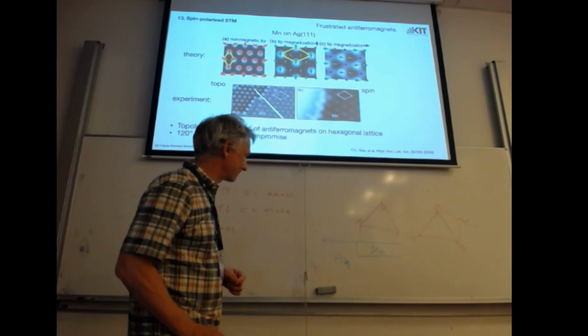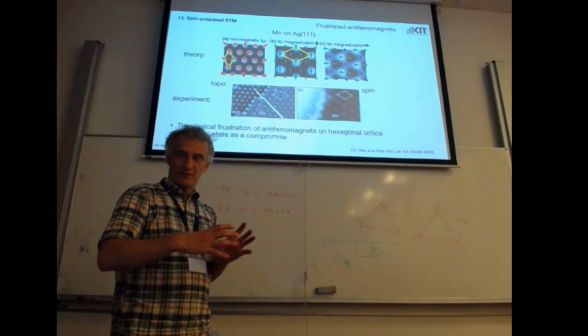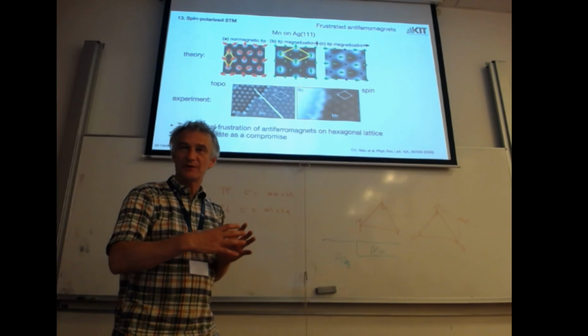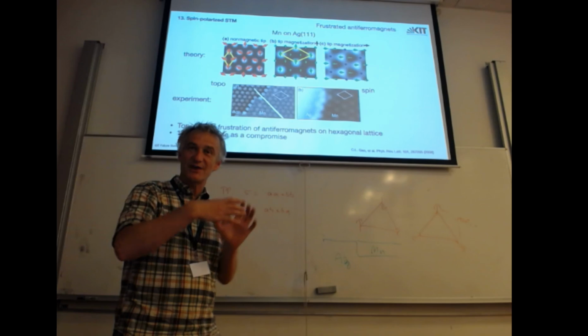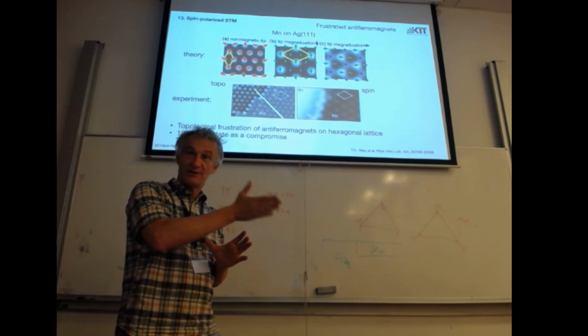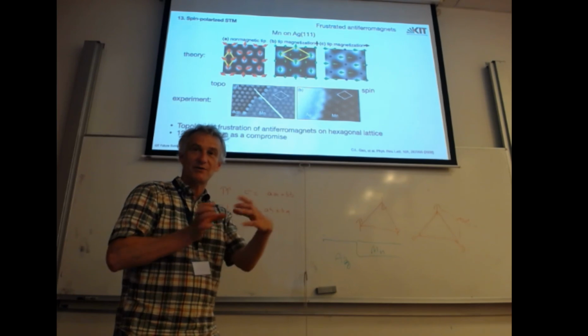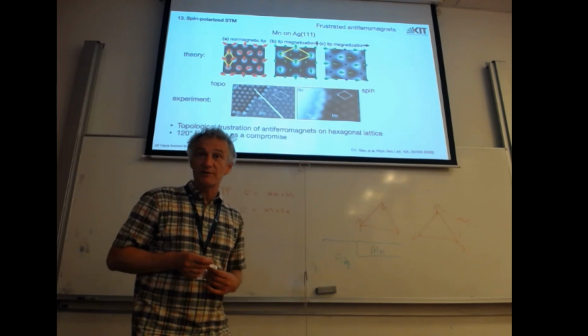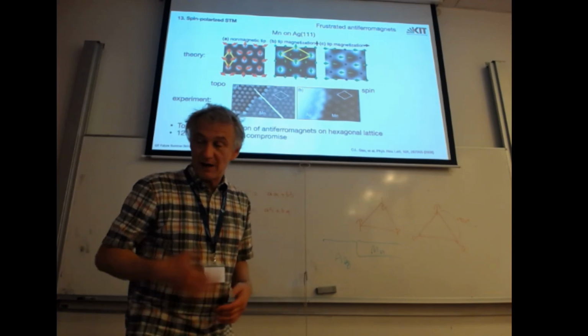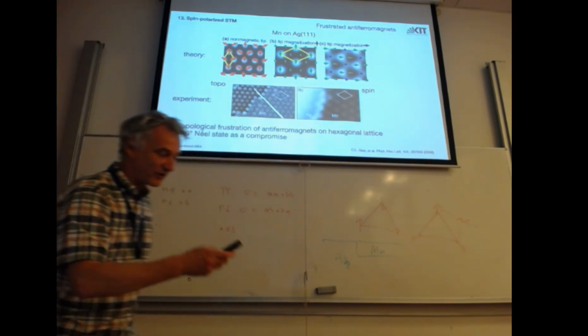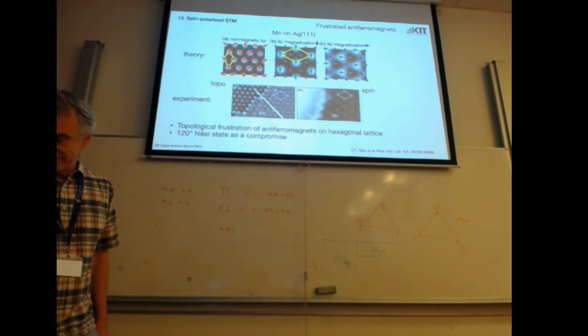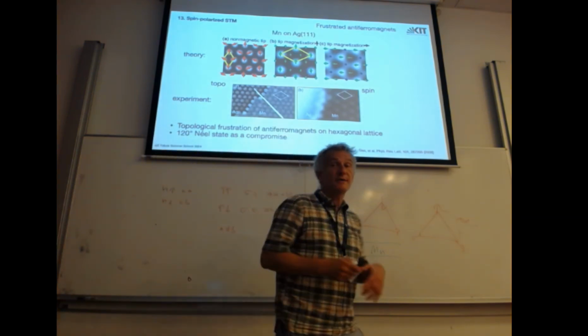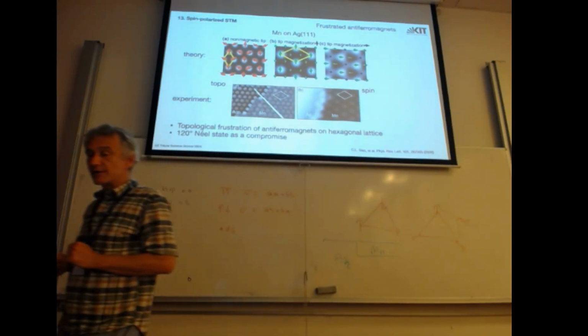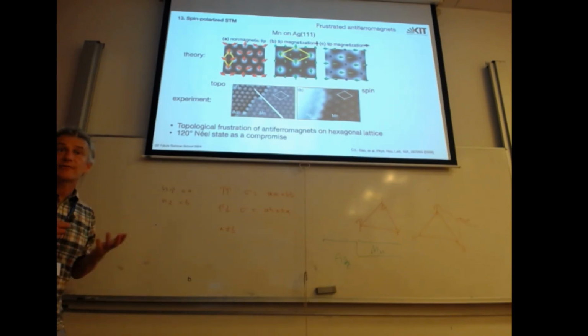In a different way, let's say we have a structure which is not four-fold symmetric, so we have two versions of it on the sample, and your tip spin polarization is like this, so you can go from this domain to another domain, and then you measure the second component of the spin polarization, and you can plot vectors. We've done that, but I didn't want to bother you about that. So it's possible, it has been done. So we can see the electron density, and with the trick of spin polarized STM, if we have very strongly spin polarized states in the sample, we can go to the energy and resolve this thing.